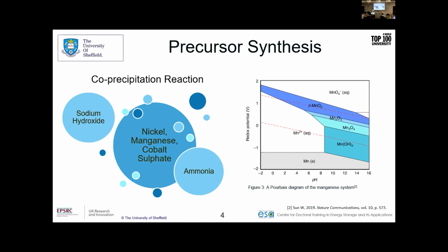To draw your attention to this chart on the other side, this is a Pourbaix diagram. And one of the key parameters with regards to the actual cations themselves, when complexing and precipitating, is to make sure that they are forming this hydroxide precursor state. So without going into too much chemistry, we've got the redox potential, which determines how oxidized or reduced a certain element is. And we've got the pH, which in this system determines how and when these chemicals precipitate and form these solid particles within the solution. And we're looking to increase this pH to a more basic area around this 10 to 15 region and form this manganese or nickel hydroxide state.